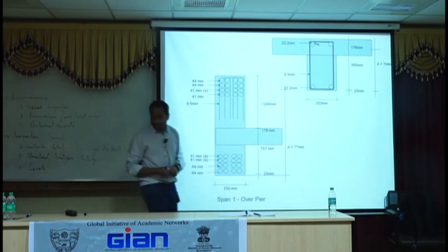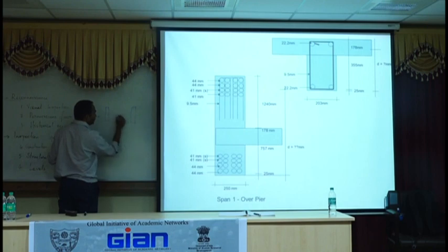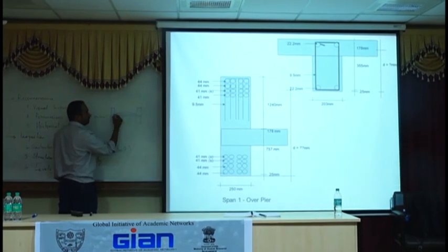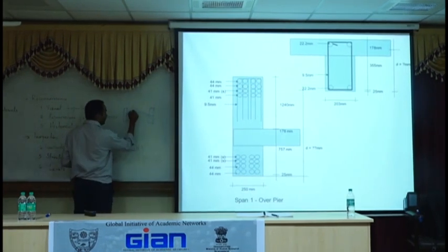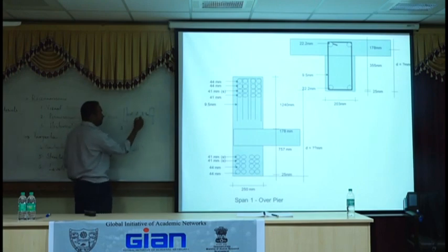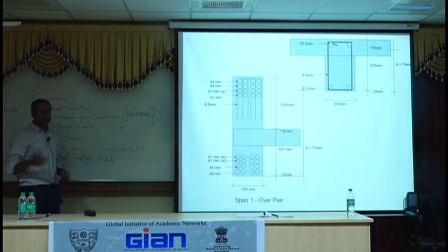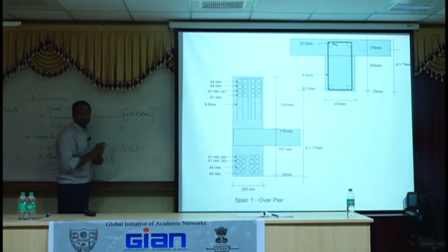So, to give you an idea of it, I know these questions are annoying, but it keeps you awake. So this is the structure, and that's the deck, and this is the road surface. What we were expecting was water was coming in because the drainage was tilted towards the south. All of these were coming towards the south and going in between it and then getting out. It wasn't jumping out because it's a big structure, but it was causing enough damage here that we could see a big rust stain here and a lot of leaching alongside.